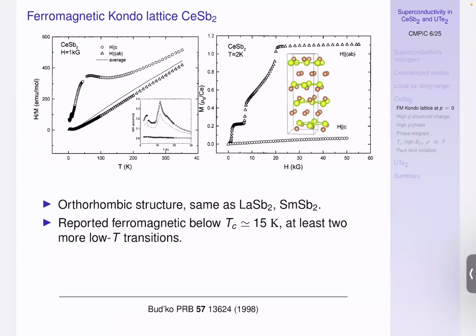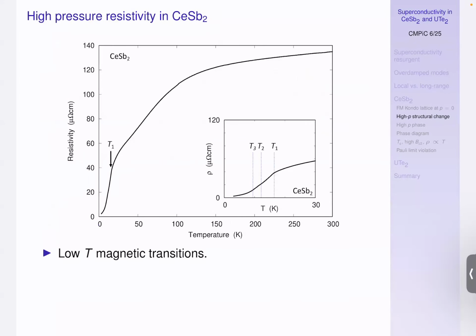Okay, so the story about cerium antimony 2 is that at ambient pressure, it has a remnant magnetization. It looks like a ferromagnet. It's actually more complicated. It has several consecutive magnetic phase transitions. But it looked like an interesting candidate for investigating a ferromagnetic cerium-based heavy fermion material, because there are not so many of those. And there's been a lot of work by the Ames group, Paul Canfield and Sergei Budko, on this material prior to our work.